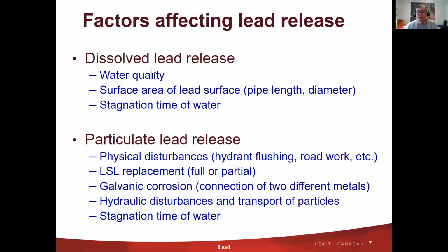In terms of factors that affect lead getting into the water, or lead release, as we call it, you can get dissolved lead release, and that's usually based on water quality, the surface area of the lead surface, so the pipe length and diameter if you're looking at a lead service line, for example, and the amount of time the water will stagnate in the pipe. It's a little bit better characterized than particulate lead release.